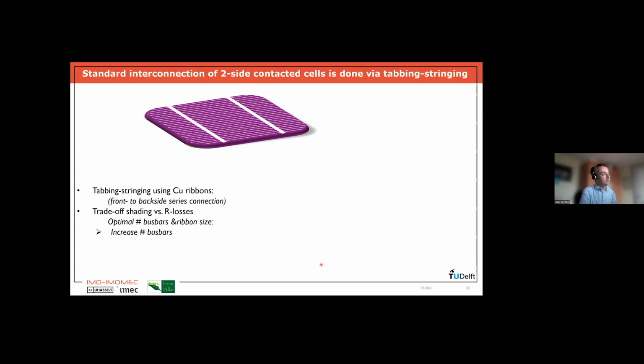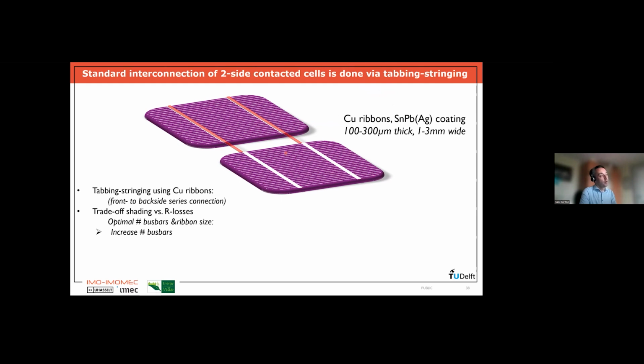So how are we now going to interconnect these wafers? You see here the first wafer, the front of the wafer, 2 bus bars, and we are going to solder on top of these bus bars so-called copper ribbons. These ribbons are made from copper. They are typically a few millimeters wide. They are a few hundred micrometers thick, and they have a coating which makes them solderable. So these copper ribbons are soldered on top of the contacts of the first cell, so at the front. We call this process, by the way, tabbing stringing. And then we take a second cell, and these same copper ribbons are now soldered to the rear contacts of the second cell. So in this way, we have connected the front polarity of the first cell with the rear polarity of the second cell.